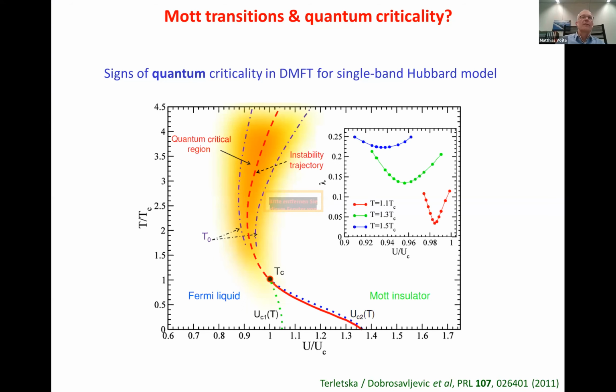Very good. So the puzzle is that in numerics, signs of quantum criticality have been seen. I'm now reporting results from this paper by Vlad Dobrosavljevic and co-workers from 2011. What you see here is the phase diagram from DMFT, and in this regime, color shaded here in yellowish orange, the electrical resistivity as calculated from DMFT has shown signatures of quantum criticality. Again, here we are above this critical endpoint—you see the critical endpoint down here where my mouse pointer is—and we're now talking about this regime up here.